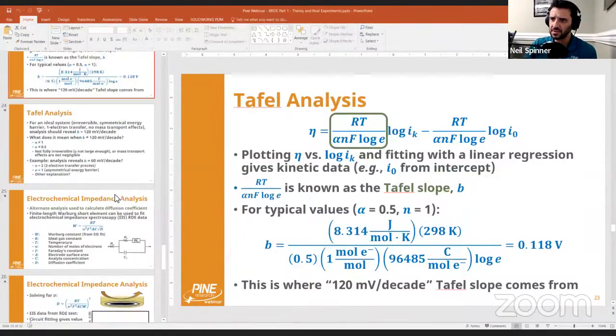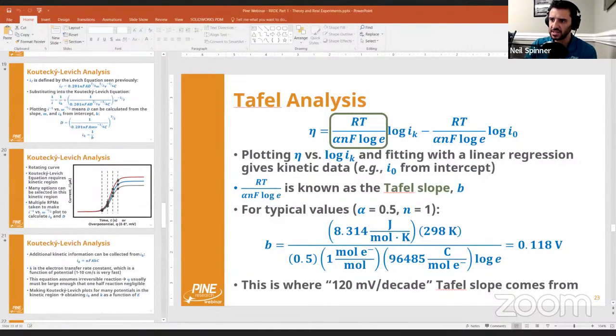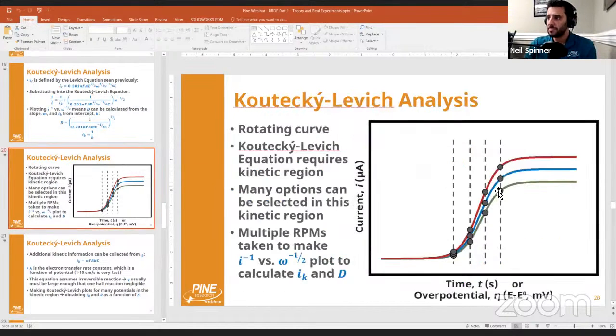I don't have an example Tafel slope in this slide. I have it in my data somewhere. But in any case, you might want to consider adjusting, like I said, where you're taking your Tafel slope, and this sort of a game, because you're like, well, is it accurate? I know what potentials I should pick, but in reality, you have that. And then the other thing, it's odd, I think, perhaps, that you're getting more electrons than fewer electrons, because, as I said, carbon isn't really a great oxygen reduction catalyst by itself.